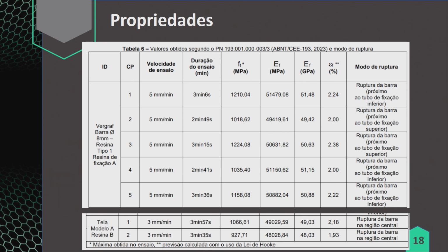So the woven direction, and we have also tested the secondary direction to determine what will be the tensile strength and if there are any losses due to the fact that the material is woven, because we are moving away from the longitudinal orientation that we see in rebars. And we wanted to know if the fibers, because they're woven, would be less resistant. So we tested this in our meshes, and the values on average are also around 1,000 megapascal. Hence, we are above the requirements, and we have a very good tensile strength compared to steel CA50. Modulus of elasticity was around 50 gigapascals also.